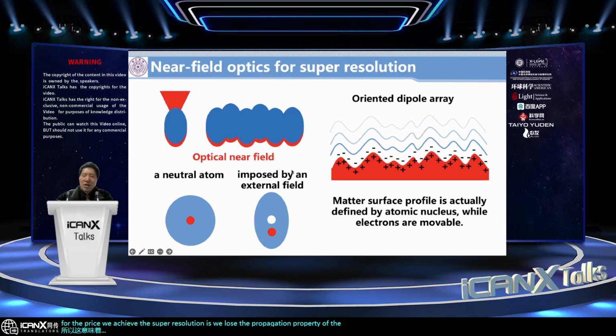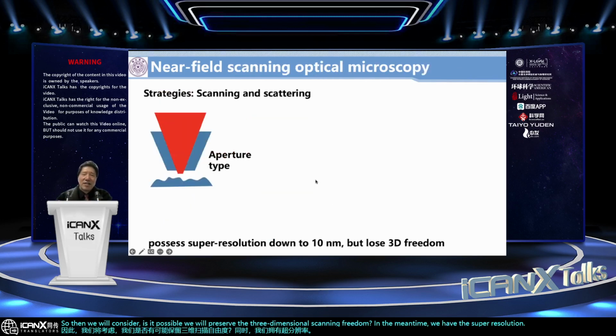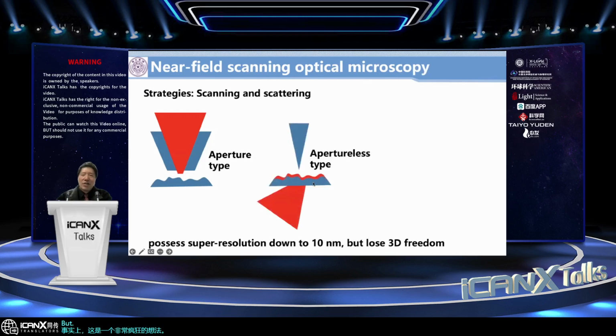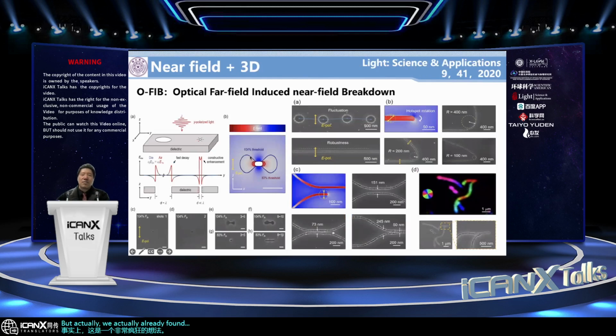So then we considered, is it possible to preserve the three-dimensional scanning freedom while we have the super resolution? Actually, this is a very crazy idea, but we already found the solution. We found that if we focus the femtosecond laser inside the material, no matter deep or shallow, we can have this kind of holes.